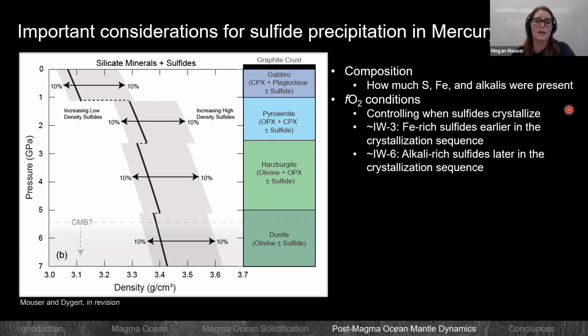But the oxygen fugacity conditions can make a difference in controlling when sulfides would precipitate. At the more oxidizing conditions, oxidizing relative to Mercury, something like IW-3, it's been suggested that you would have precipitation of iron-rich sulfides earlier within the crystallization sequence, and therefore deeper within the mantle. But if you had more reducing conditions, then it's probable that the alkali-rich sulfides would precipitate later and thus shallower within the crystallization sequence.